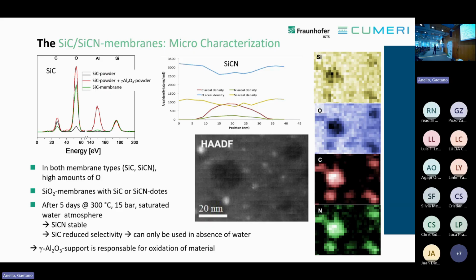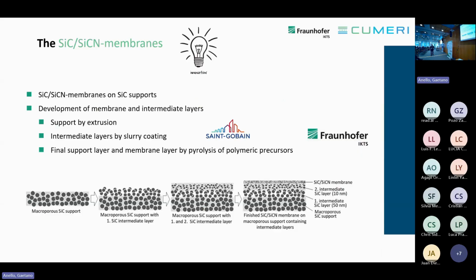Well, and where is the oxygen coming from? The idea was that it's because of the substrate. We have a gamma alumina layer below the membrane, and the oxygen is moving into our membrane. Therefore, we got the idea, well, let's use an oxygen-free substrate, and this could be silicon carbide. Saint-Gobain is a producer of microfiltration membranes made of silicon carbide. Therefore, they had the task to prepare the substrates by extrusion and then to prepare intermediate layers by slurry coating. And on top of the final layer, we tried to make the polymeric precursor. However, the problem is that the membranes Saint-Gobain has produced up to now have quite big pores, also in the final layers, and the pores are much too big for coating with a polymer.